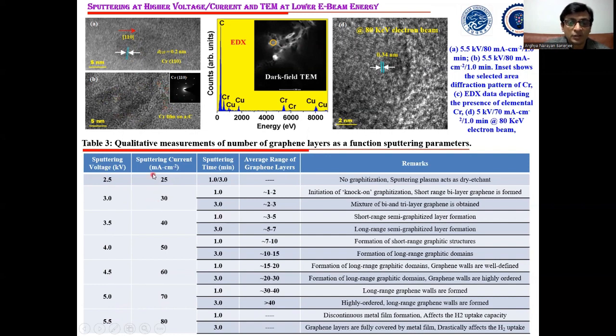So therefore, this table is showing that when we have very low sputtering parameters, no graphitization is observed. When you slowly increase the sputtering parameters, the average number of graphene layers increases, and ultimately beyond a certain optimum limit of the sputtering parameters, a metallic film is formed, which actually deteriorates the hydrogen storage capability. Therefore, we stick to our sputtering parameters up to this optimum value.